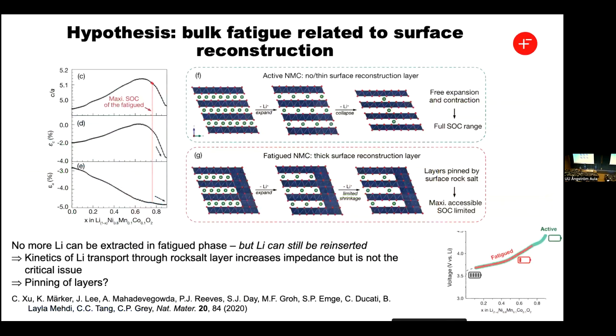So what Chao proposed was that in the initial material, the material can expand and contract. But when you start to put a rock salt structure on the material, this rock salt structure has a spacing that matches the open structure at the top of its most expanded state. That rock salt structure pins it and really prevents that collapse. So at least that's one mechanism for why, when you've got such a thick rock salt structure, it's very difficult to pull more lithium out of the material.